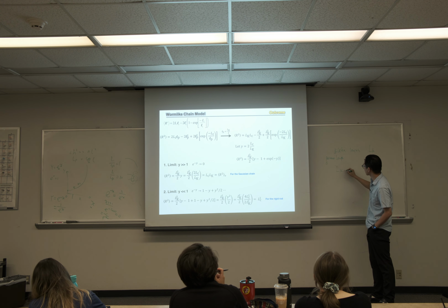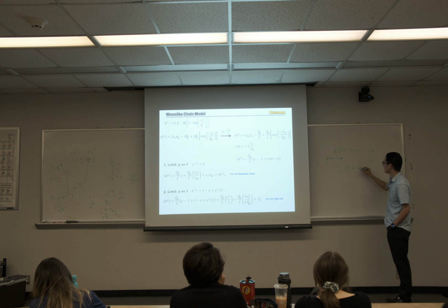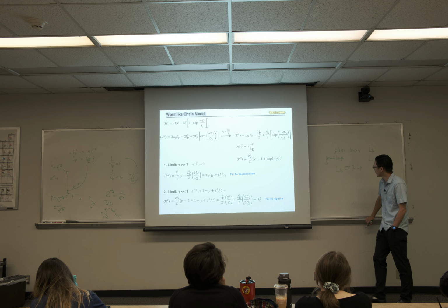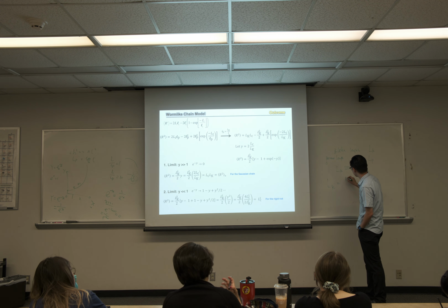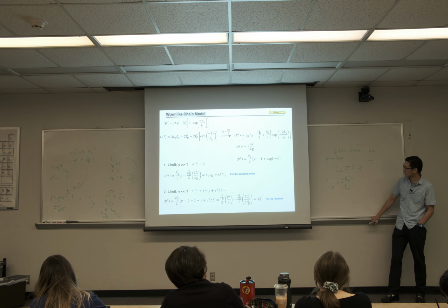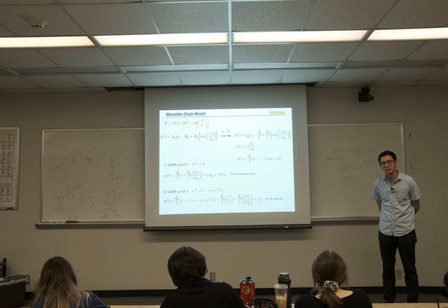And LK is typically closer to twice of LP. And the definition of Kuhn segment is very easy. Defined by end-to-end distance, we can use REE squared divided by contour length. So it's a coil size normalized by its total length.